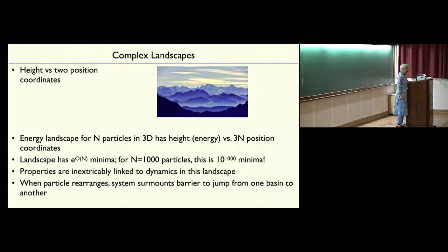But another way to explore it is by just dragging the system through. In other words, by applying some shear, you drag the system through the landscape and deform the landscape. If you're doing it at zero temperature, you're deforming it so that you're always sitting at a minimum. But by doing this, you go from one minimum in the unsheared landscape to another. So you rearrange that way.